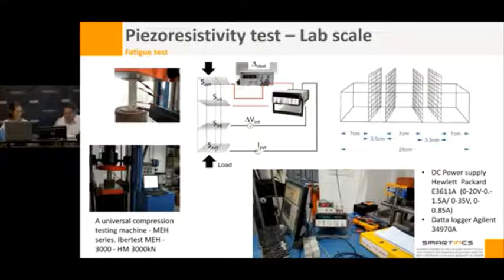As a constant current is applied along the tension or compression load, it is possible to see the variation of resistivity during the test. We verified the hygrothermal condition at the time of the test, because we see that this is important, the humidity of the sample. It was very important to control the hygrothermal conditions. The sample was stored in a cooling chamber before testing.